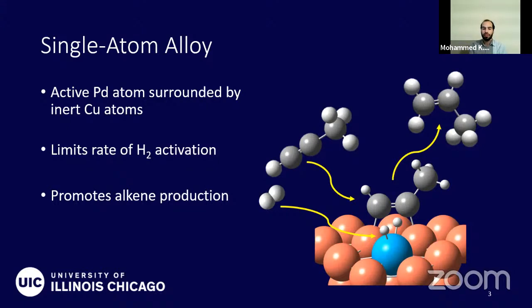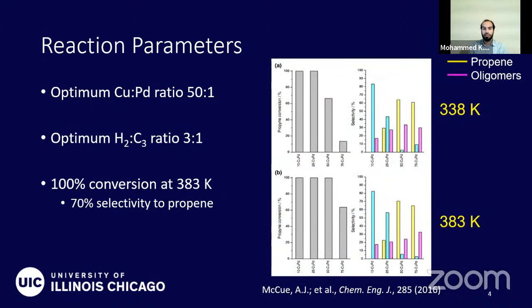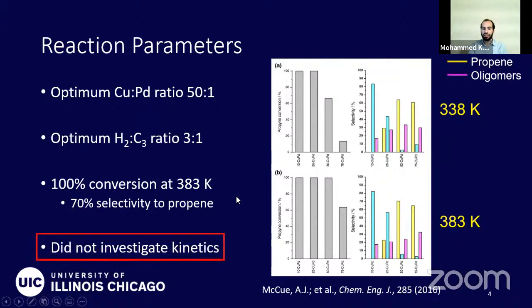But using this single atom alloy approach, we can take a single atom of the active metal and embed it into the inert surface. We can control the limit of hydrogen activation such that we promote the production of the alkene instead of the alkane or polymers. And so we're building on the work of McCue et al., who laid the groundwork for this project, and they basically determined the optimal ratios of copper to palladium and hydrogen to hydrocarbon, as well as the temperature that's most efficient for this reaction. So they found at 383 Kelvin, they get 100% conversion, and they have very high loadings of copper. And so here, this 50-to-1 copper palladium ratio provided the highest selectivity to alkene, which is the yellow bar here. But they did not investigate the kinetics of this reaction, so that's what we set out to do.